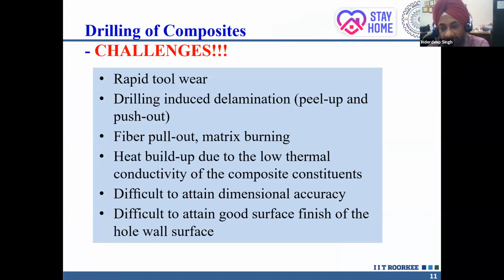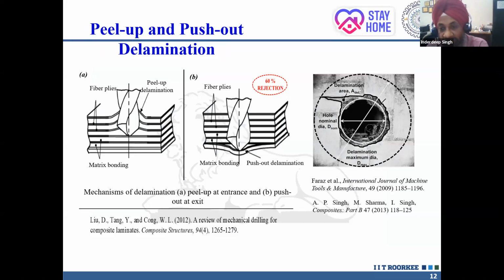It is difficult to attain dimensional accuracy because of the fiber pull-out and sometimes chipping of the matrix, which is brittle in nature. That can also make it hard to attain very high dimensional accuracy in the holes that are produced. And the surface finish of the hole wall is also sometimes a challenge, because the fibers are protruding out from the hole wall and we are not able to get a good quality hole. Whatever I have been speaking, this is a very important slide to explain that.